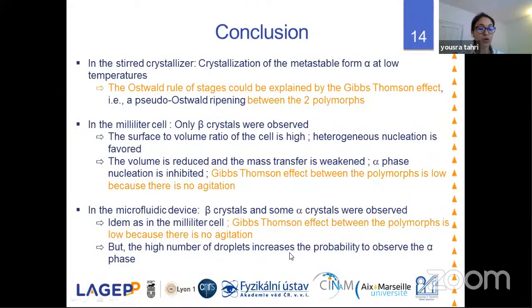So to conclude, in the stirred crystallizer, we observe the crystallization of the metastable phase alpha at low temperature, in accordance with the Ostwald rule of stages. And we could explain this by using the Gibbs-Thomson effect, which is a pseudo Ostwald ripening between the two polymorphs. In the milliliter cell, only beta crystals were observed. This is because of the promotion of heterogeneous nucleation. Also, the Gibbs-Thomson effect between the polymorphs is low because there is no agitation, so we don't have this competition that is promoted between the two polymorphs. And in the microfluidic device, we also observed mainly the beta crystals because the Gibbs-Thomson effect is not promoted, but the high number of droplets increases the probability to observe the alpha phase.